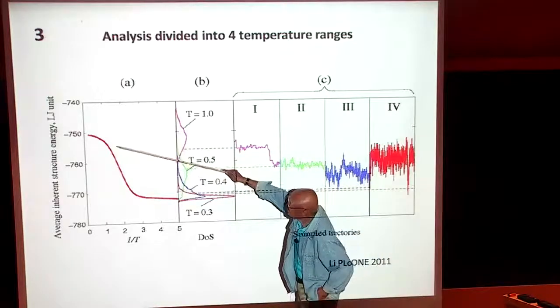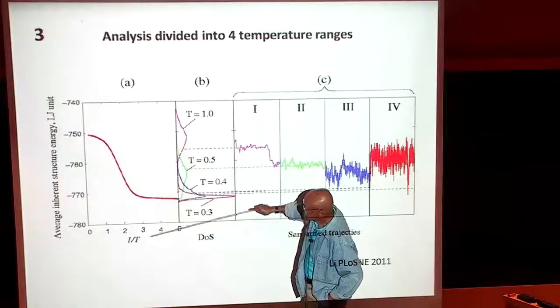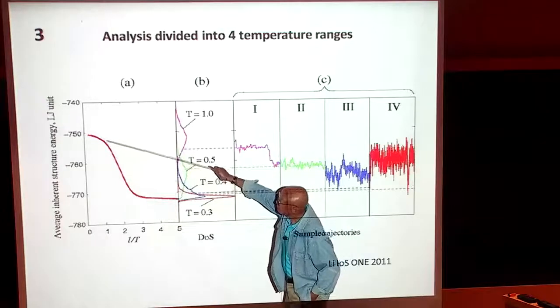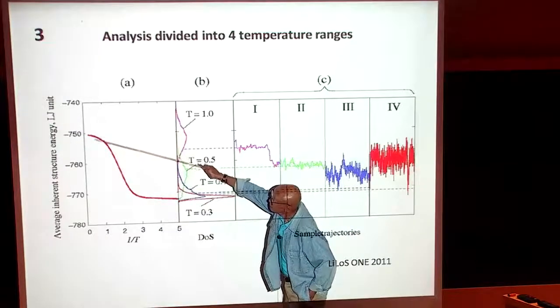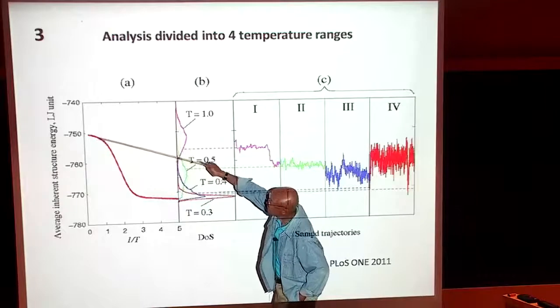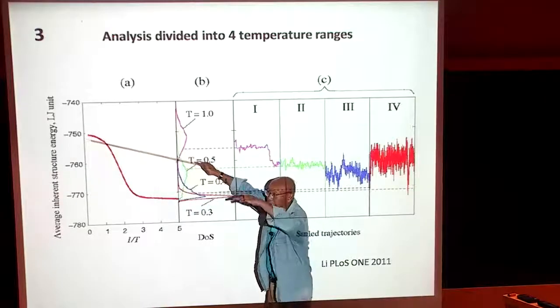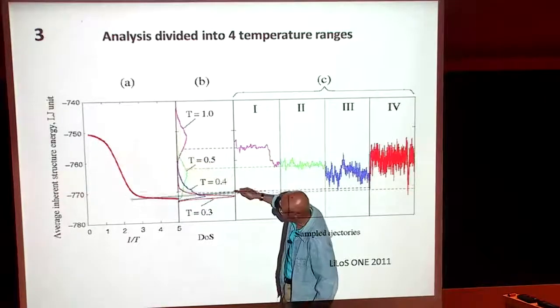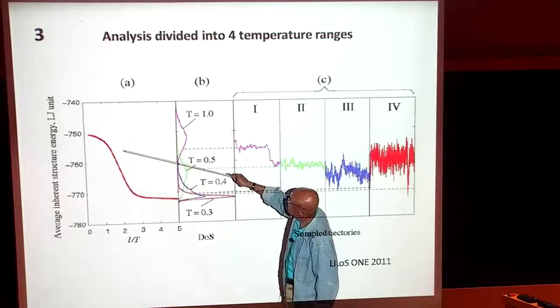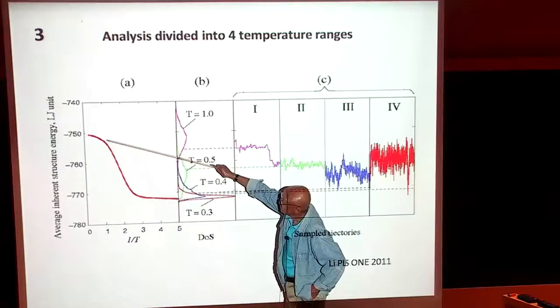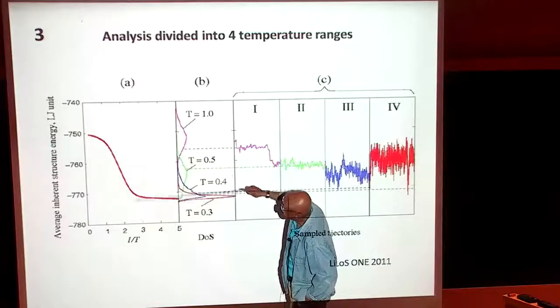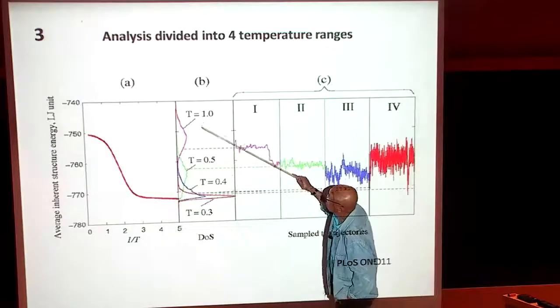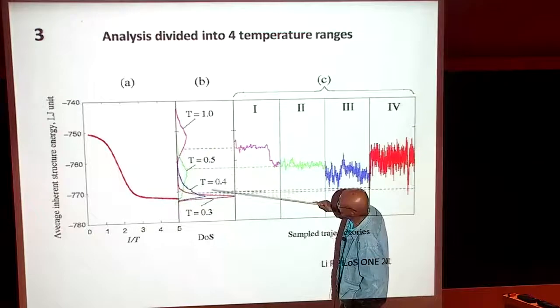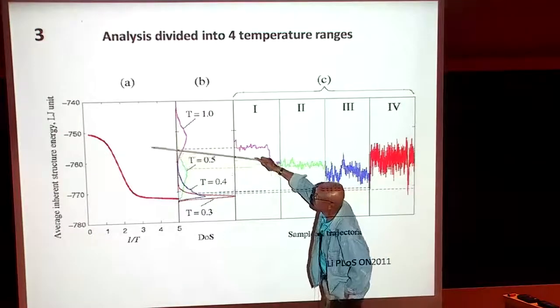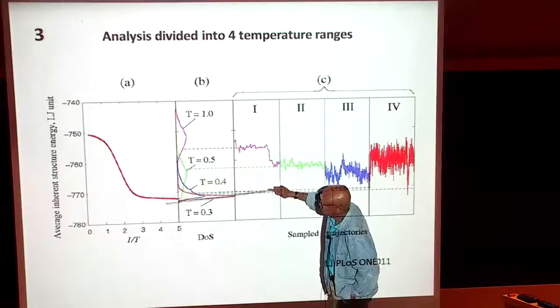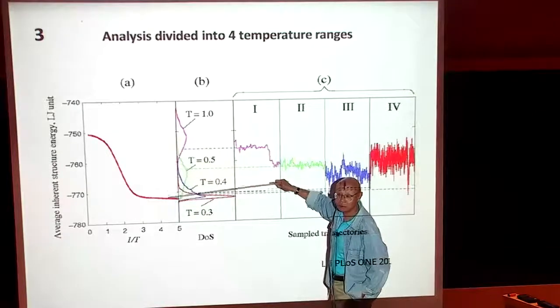So at high temperature, 1 over T is small. The inherent structure energy is fairly small, the well depth is low, and then when you get down to lower temperature, it drops. So we decided to break this temperature range into 4: temperatures 1, 0.5, 0.4, 0.3. So we prepare 4 samples.